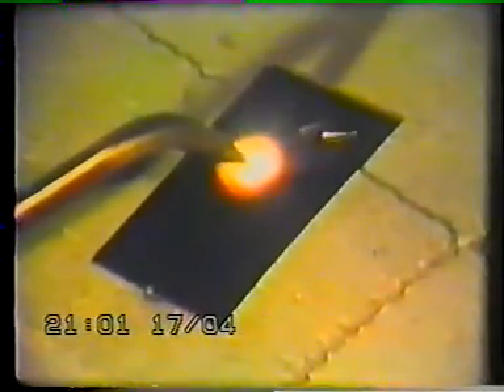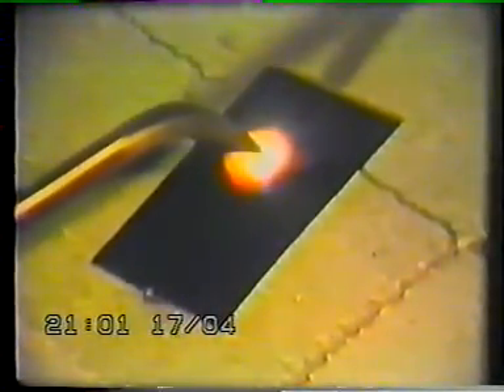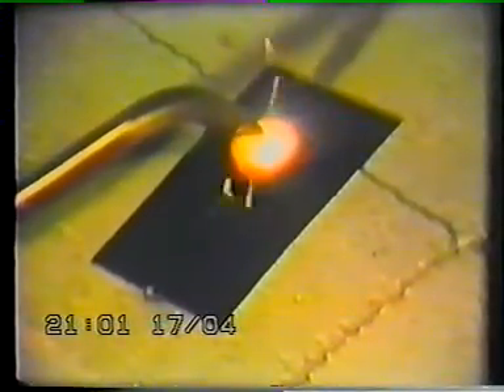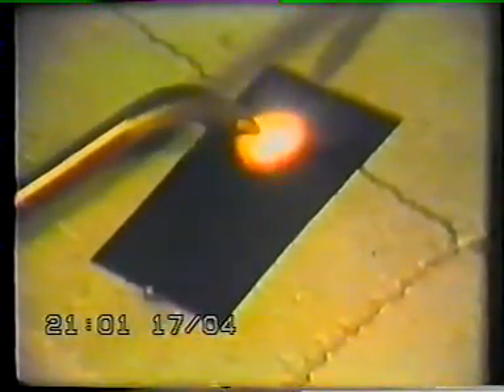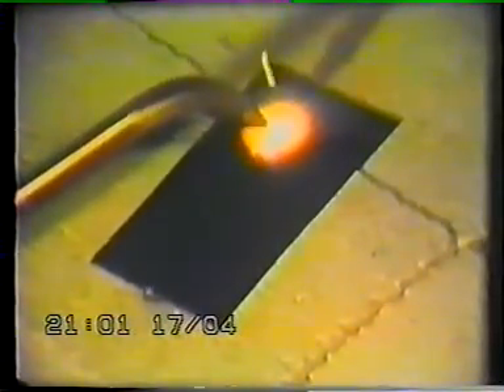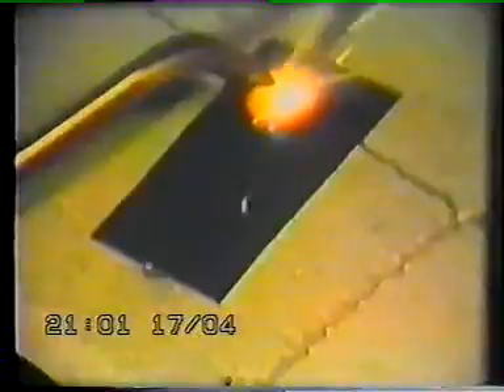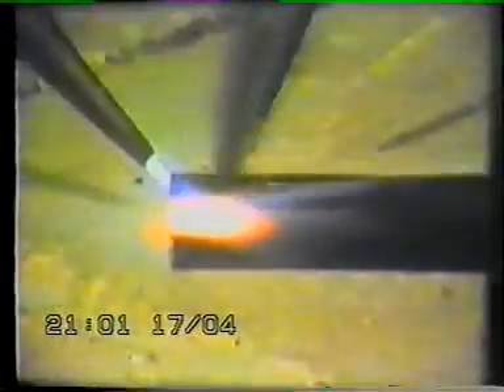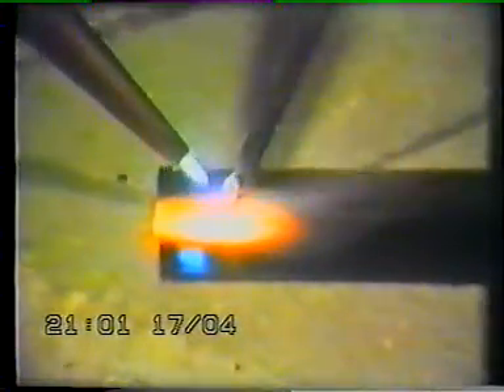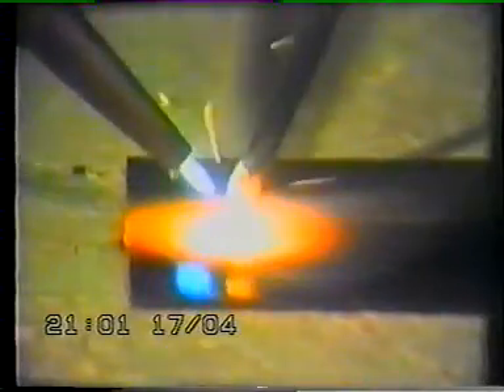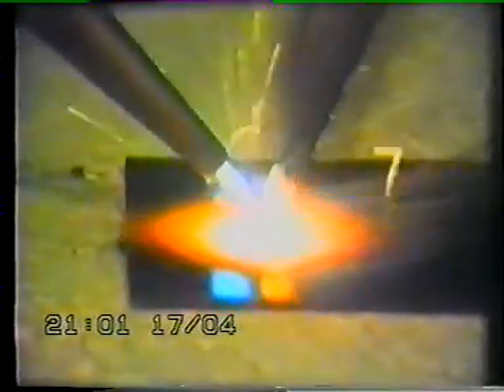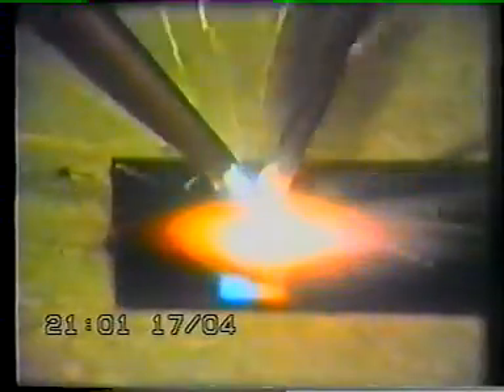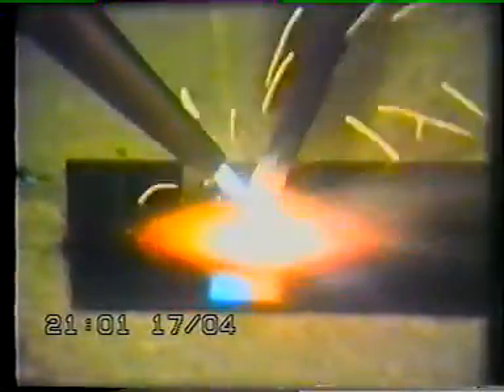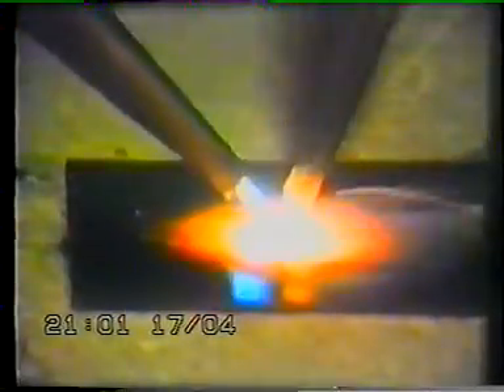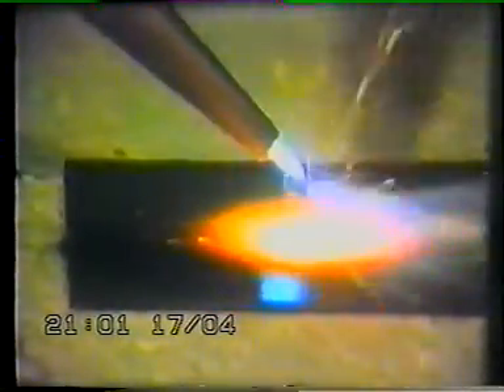Don't hold the torch too long in one spot. It will burn a hole in the metal. Remember not to allow the cone to touch the puddle. It is sometimes necessary to use a welding rod to reinforce the metal. After the puddle starts to form, add the welding rod to the middle of it. Direct the flame on the metal, but not on the end of the rod. Don't melt the rod so that it drips. Keep it in the puddle as long as reinforcement is needed.